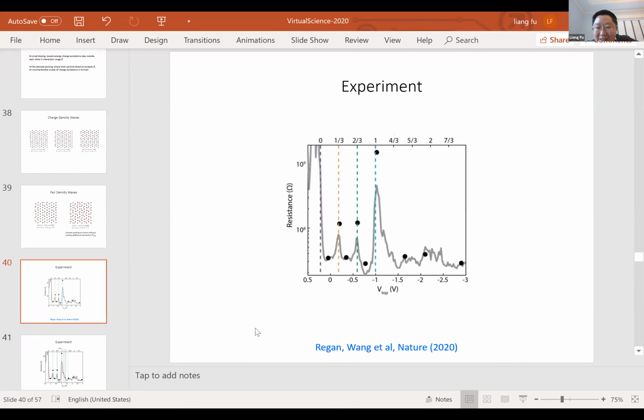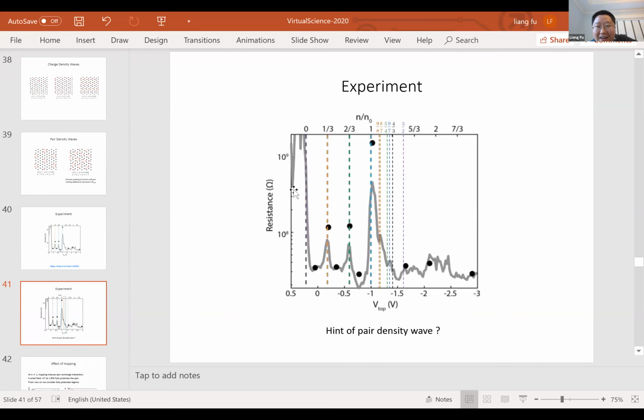So now let us look at the experiments. Again, this is from the Berkeley group. They identify these peaks at filling 1, 1/3, and 2/3. The authors didn't really discuss features above n equal 1. This may well be artifact, but one certainly sees additional peaks. Kevin took a close look at this data, and interestingly, at least with a loving eye, he can identify these extra peaks. You can see here that there's one extra peak, which is close to 1 + 1/3, but actually it's much closer to 1 + 2/7.